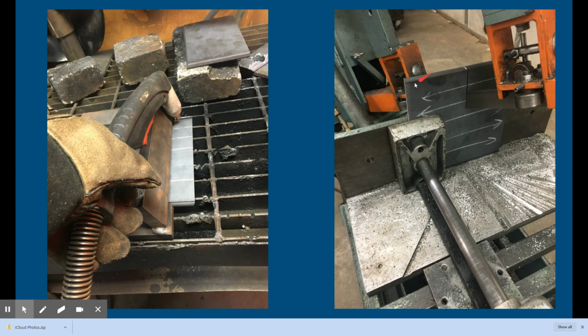So you can see this is how we would cut that piece. It comes out of the bandsaw, or out of the shear, about 7.5 inches. We'll find the center, and we want to cut it right down the middle so we get equal pieces. This would be for your 3G, because you end up with then a 22.5 and a 22.5. If you're cutting this for a 2G, we would have to cut one piece square on the end to make sure that we have a true single bevel versus a V groove.